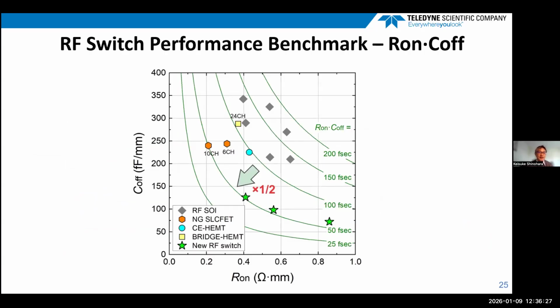So here I show the RF switch performance benchmark of our technologies in comparison to the RF SOI technology, as well as Northrop Grumman's SLCFET technology. The blue data points are from CE-HEMT, and the yellow square is for the bridge HEMT with 24 channels. By using these technologies, we could reduce the RonCoff figure of merit better than the RF SOI, but it was not as good as the SLCFET.